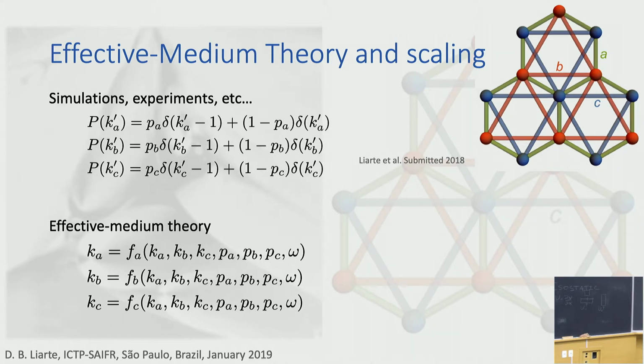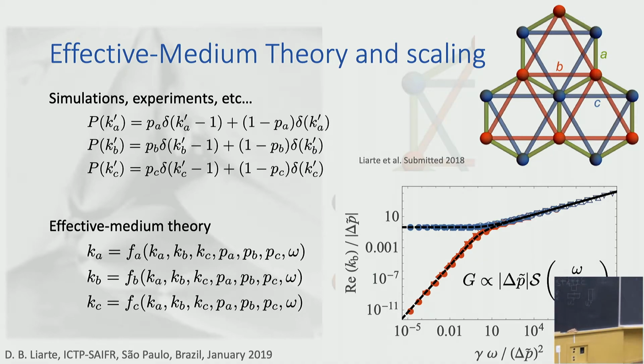So you solve for these equations as a function of PA, PB, and PC, and that can give you the critical properties of the jamming transition, as I'm going to show you in the next slide. Just to anticipate a little bit, for instance, you can do scaling collapse plots. Those are signatures of phase transitions. And I'm showing symbols here that correspond to scaling collapse plots near the jamming point, and some analytical curves that you can find from this effective medium theory. And the important thing is that the shear modulus for jamming satisfies exactly the same kind of critical behavior that you observe here, and that we have an analytically tractable model that you can use to describe this jamming transition.